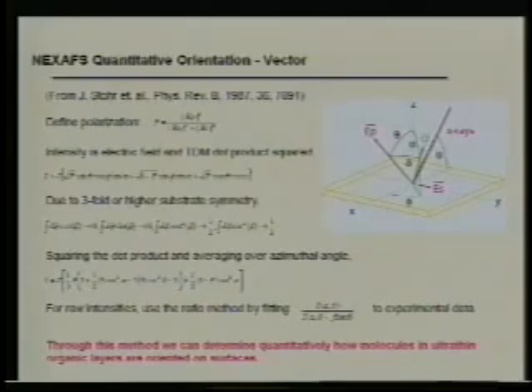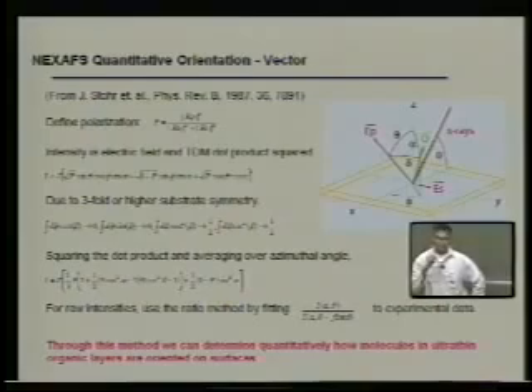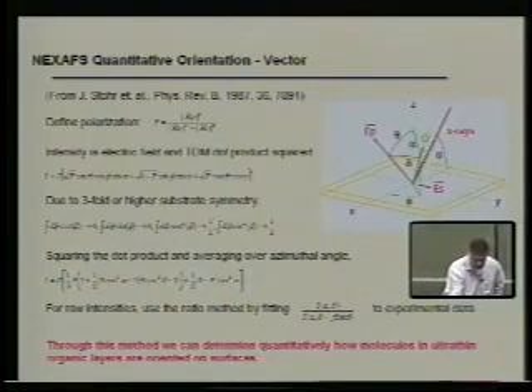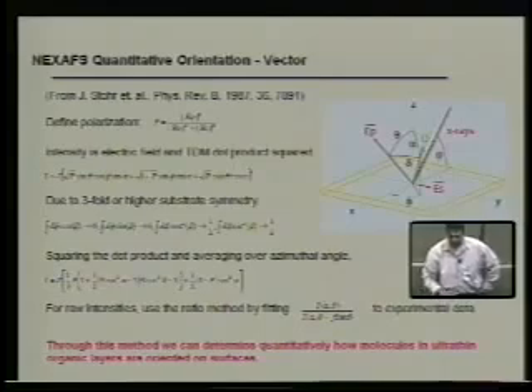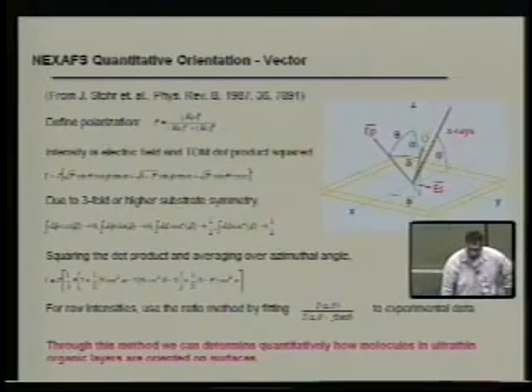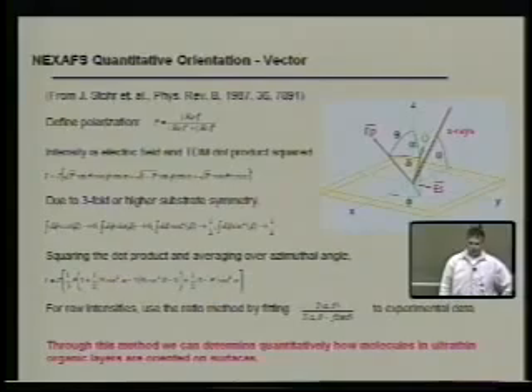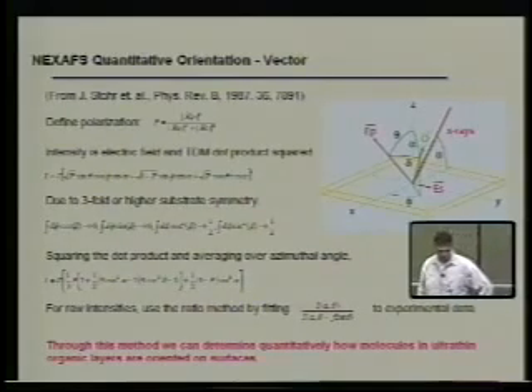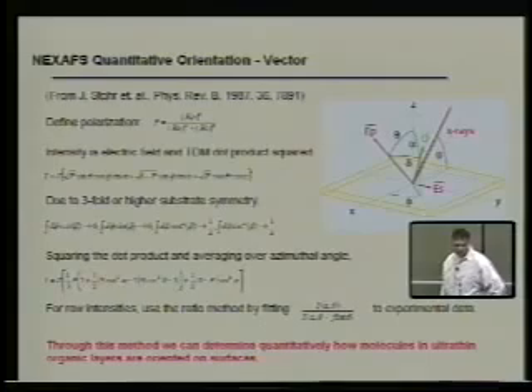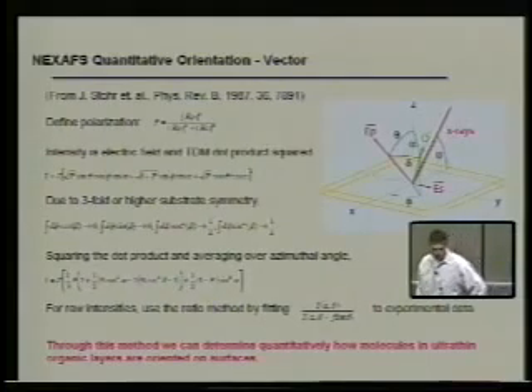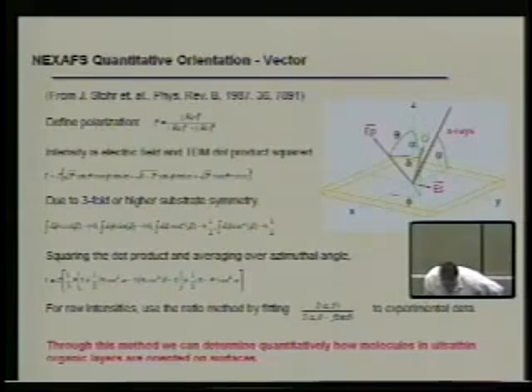works in these materials. So if we look at the polarization of these materials, you can have polarization, in this case, for the vector. This is for molecules bonded to surfaces. And you can see that you have the I term here. That's the intensity, and it's related to theta, phi, and delta. That's basically the dot product of the electric field with the transition dipole moment. So here you have an intensity versus theta, phi, and alpha in this case.